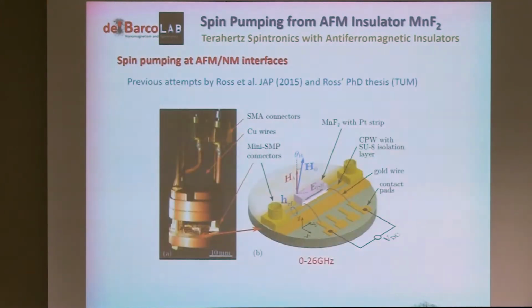Now I can go to the experiments, but before going to my experiments, I will describe Ross et al.'s experiments. So these guys actually tried the same experiment by placing a single crystal of manganese difluoride, this cube here that you see, where they polished the surface, deposited a strip of platinum on top of it, and placed the whole thing on top of a coplanar waveguide. And then they pass microwave radiation through the coplanar waveguide to irradiate the sample, and from this irradiation eventually generate the spin pumping that will be measured or converted into voltage because of the inverse spin Hall effect, right?